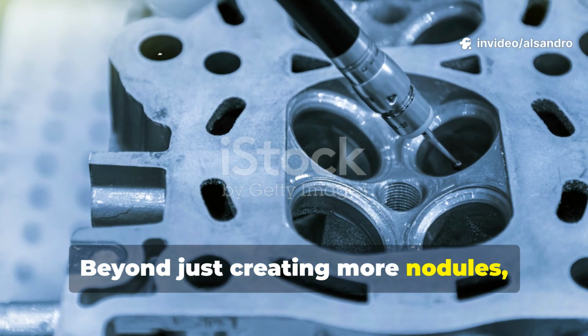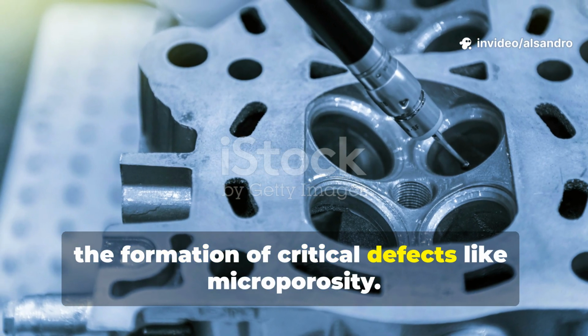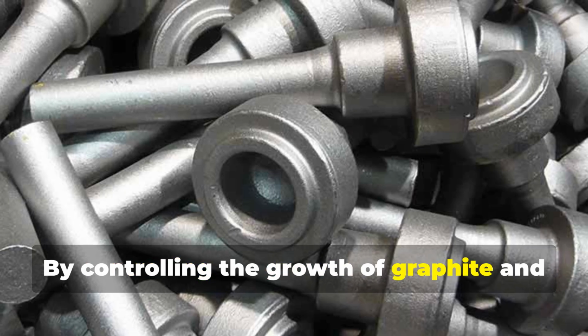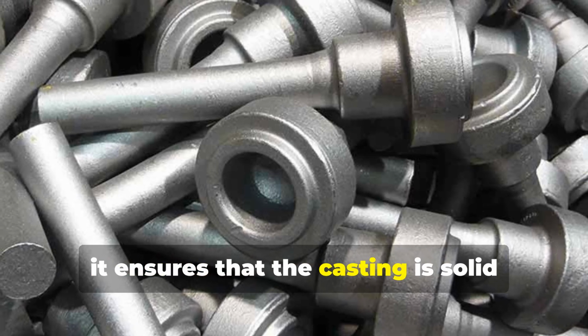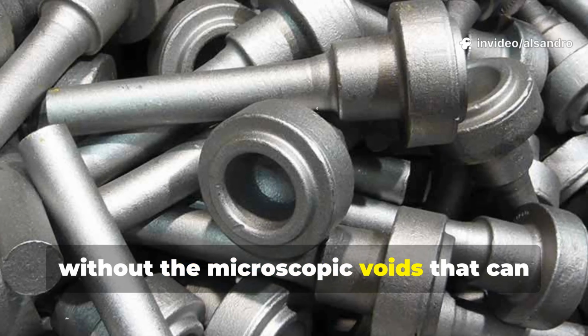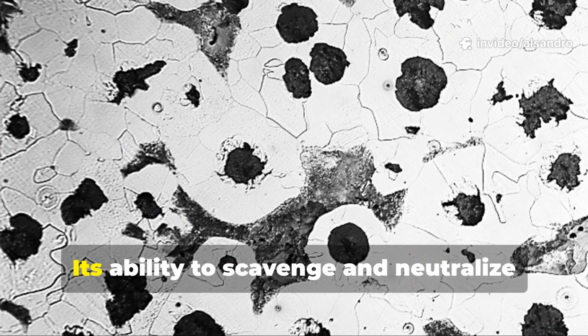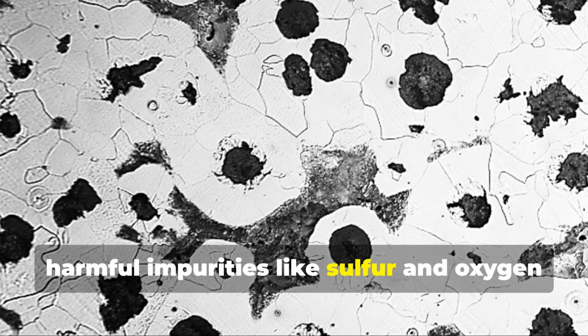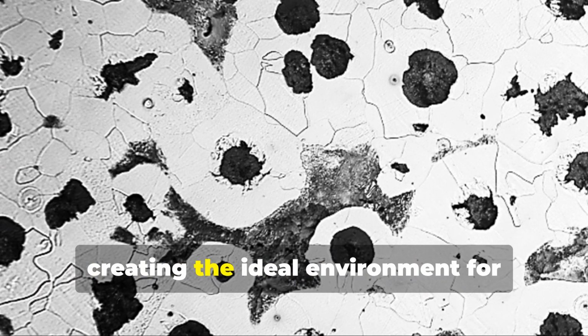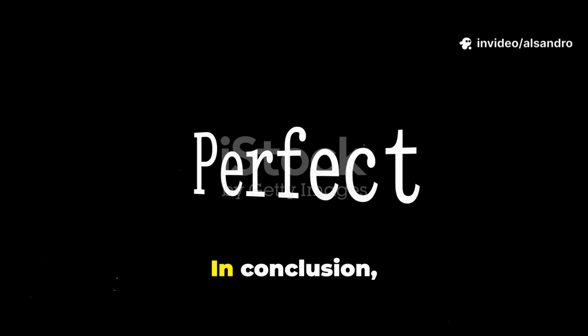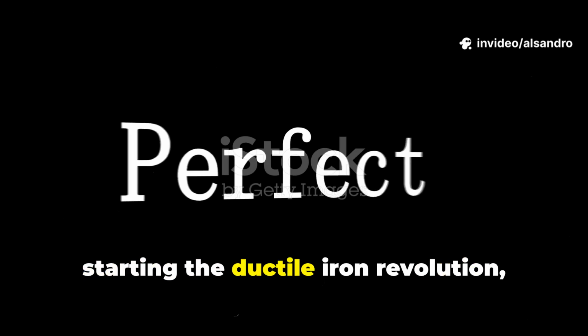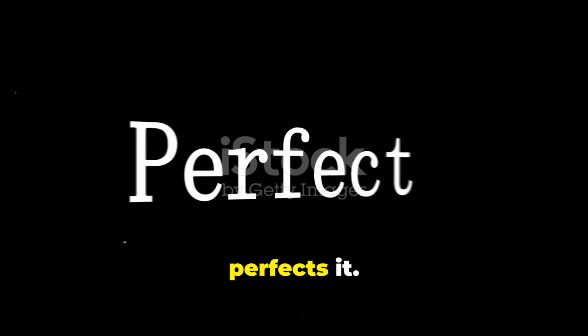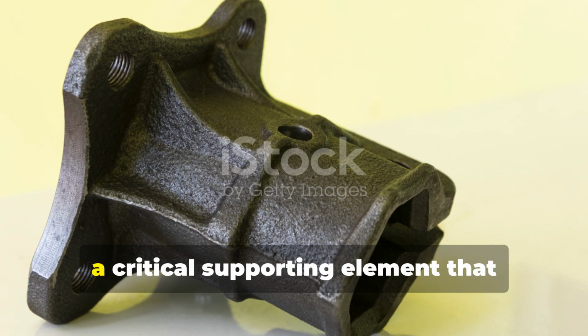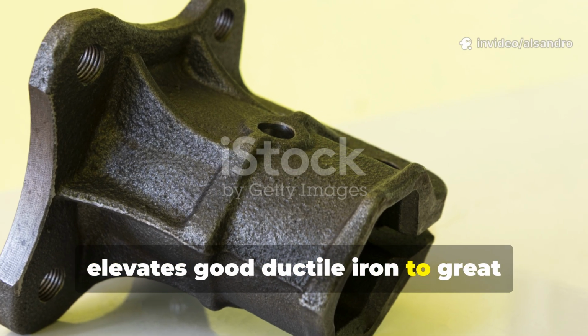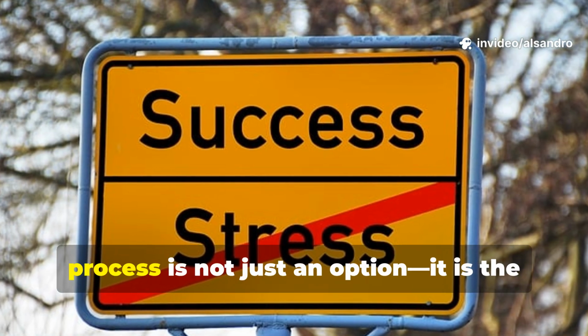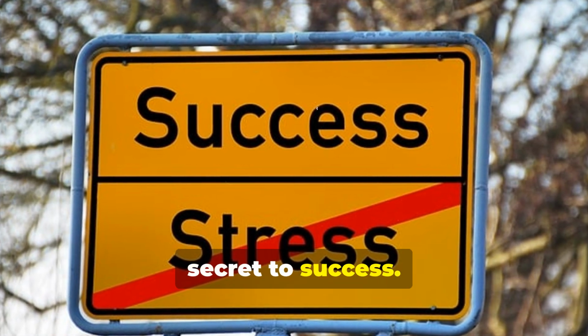Beyond just creating more nodules, lanthanum is instrumental in preventing the formation of critical defects like microporosity. By controlling the growth of graphite and the solidification of the iron, it ensures that the casting is solid through and through, without the microscopic voids that can compromise its strength and durability. Its ability to scavenge and neutralize harmful impurities like sulfur and oxygen further purifies the melt, creating the ideal environment for perfect nodule formation. In conclusion, while magnesium may get the credit for starting the ductile iron revolution, lanthanum is the unsung hero that perfects it. It is an indispensable ingredient, a critical supporting element that elevates good ductile iron to great ductile iron. Incorporating lanthanum into their process is not just an option, it is the secret to success.